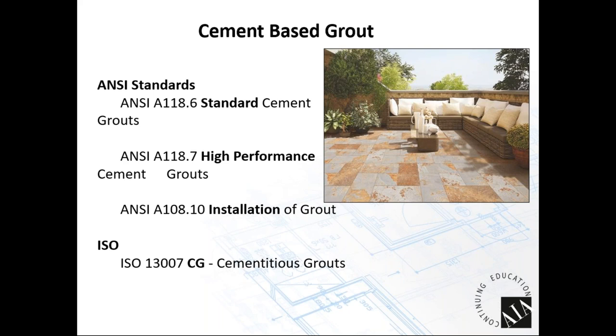Your typical Portland cement grout is Portland cement with various additives in it to hold in a retention of water so it cures, and pigments in it for the coloring. One of the problems with a traditional Portland cement is moisture getting into that. A lot of times we can end up with efflorescence or salts in the grout, discoloration of the grout, too much water in it washes out color as they're putting it up. On a hot day, the installer will overwash, overmix, and have problems with it.